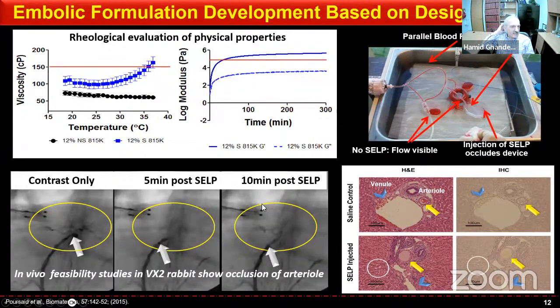Some of the in vitro studies that we did, we needed to make sure that we reached the viscosity that we needed to reach, and SELP815K gave us that at 12% weight. Shearing of these polymers was extremely important because the silk blocks actually interact with each other, and if you shear them, you get this linearity of the polymers that enables the interactions of the silk blocks in a better fashion, so that shearing proved to be very important. This is non-sheared, which doesn't give us that viscosity, but the sheared polymers do give us that. For the modulus of elasticity, we reached the limit that we wanted to.